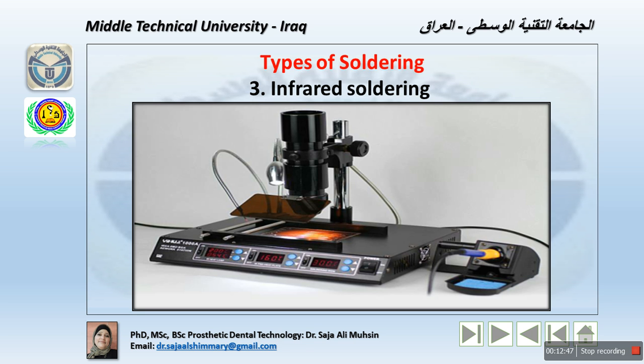Solder for gold alloy melts at between 1420 Fahrenheit and 1500 Fahrenheit, while the solder for cobalt chromium alloy melts at about 1676 Fahrenheit.